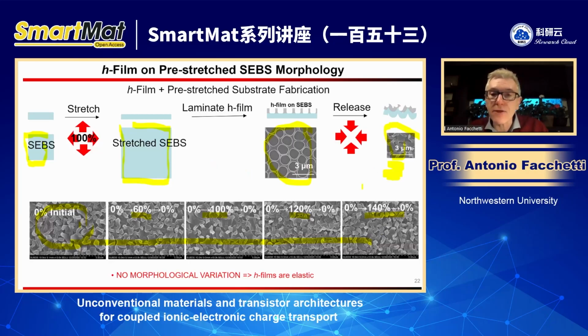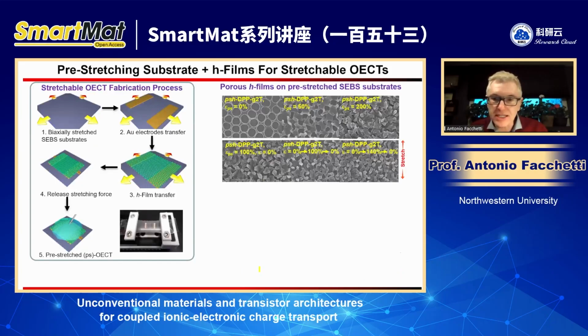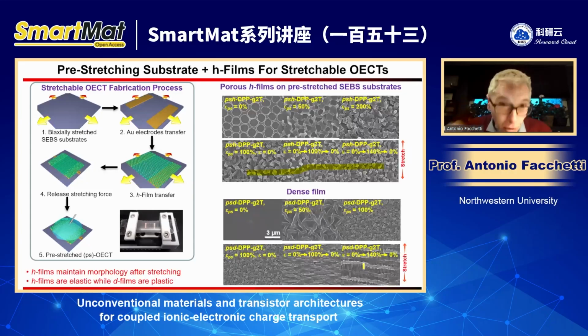If you do the same thing with the dense film, you start stretching, and you see that after stretching, the morphology changes. So the dense film does not crack, but the morphology changes. It tells you that the dense film on a pre-stretched substrate is a plastic film, but not an elastic film. So in order to get an elastic platform, you need to have a honeycomb film. This is the message. This is very important.